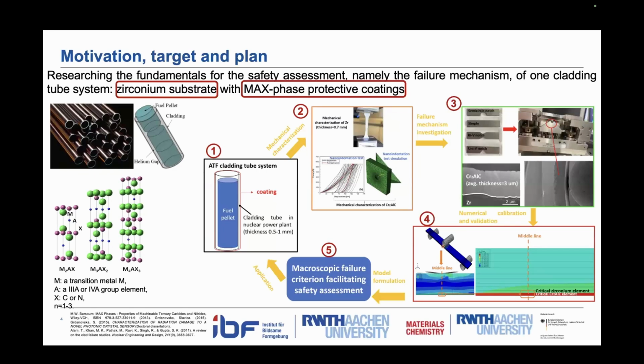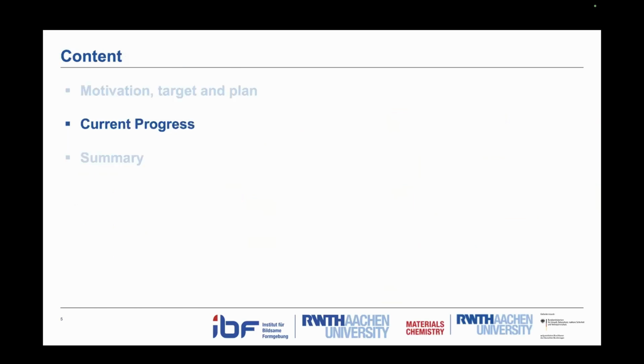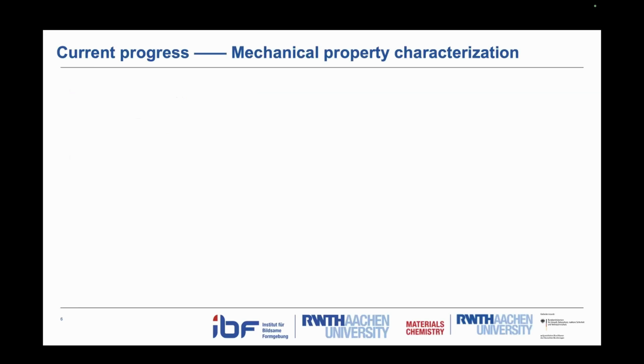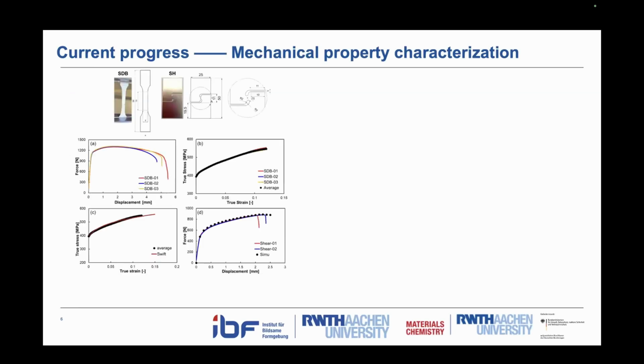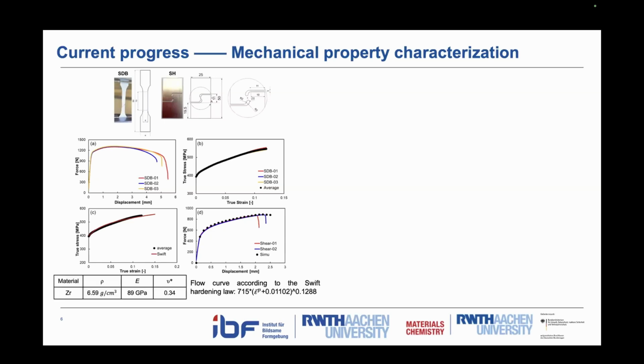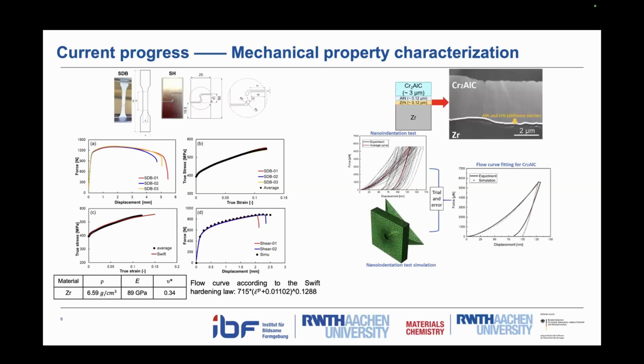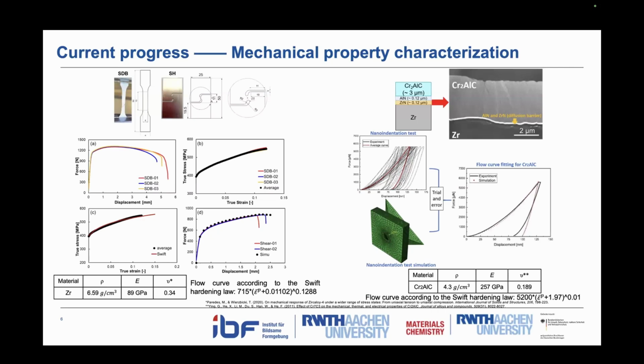Following this routine, what we have achieved is, first of all, the basic mechanical property characterization. For zirconium, we have carried out uniaxial tensile tests on standard dog-bone samples and also shear samples. Based on the flow curve, we characterized its mechanical properties and fitted its flow behavior based on the Swift hardening law. For the MAX phase material, we have chosen its member chromium aluminum carbide. We did a nanoindentation test, and coupled with simulations, we characterized its mechanical properties and also fitted its flow curve based on the Swift hardening law.